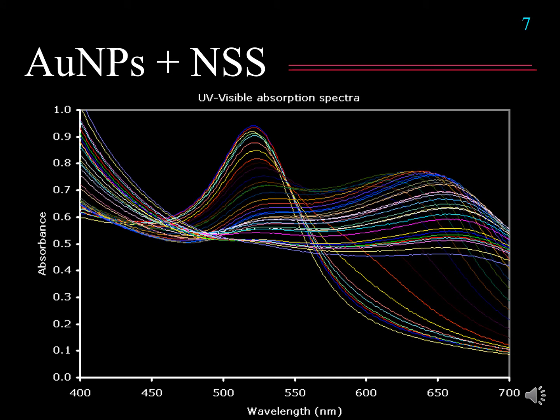So after the ionic strength is increased, then the solubility of the citrate changed. So the absorption of the citrate ion onto the surface of the gold nanoparticle is changed. By this kind of change, what we can see is that the gold starts to aggregate, the nanoparticles start to aggregate together, increasing the size of the nanoparticles into the micrometer scale and so on.